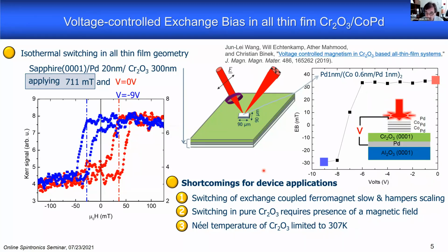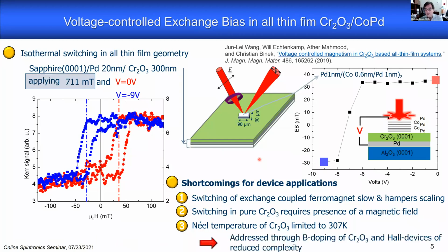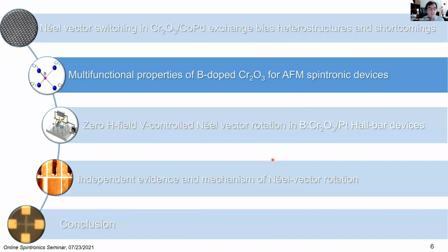The Néel temperature of 307 Kelvin of chromium oxide is not sufficient to make a functioning device, especially not in a CMOS environment. It turns out that all of these problems can be addressed by boron doping. Interestingly enough, we started the boron doping business to address this problem, but the other problems will also be addressed as I show during the next slides.